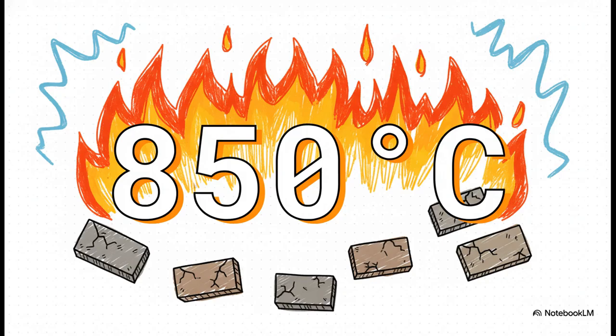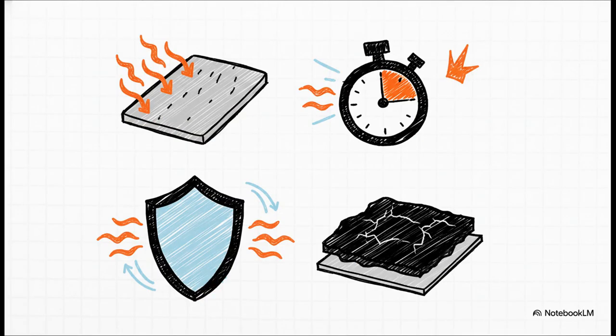But they don't stop there. Not even close. The temperature gets cranked all the way up to 850 degrees Celsius. That's over 1,500 degrees Fahrenheit. There's a process called a dry corrosion test, where they basically bake the coatings at this insane temperature for up to 6 hours, just to see if they have what it takes to last. And it's not just about the raw temperature. More advanced tests, like cone calorimetry, look at performance under intense heat flux. They start asking much smarter questions, like how long does it take before this thing actually catches fire? How good is it at insulating whatever is underneath? And maybe most importantly, when it does burn, does it form a nice, stable, protective layer of char, or does it just crumble into ash?